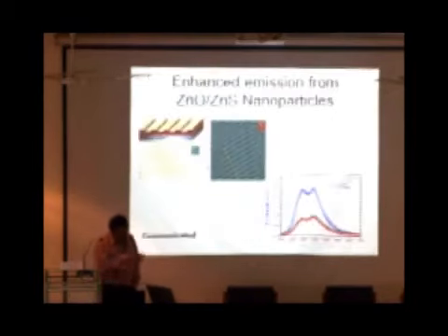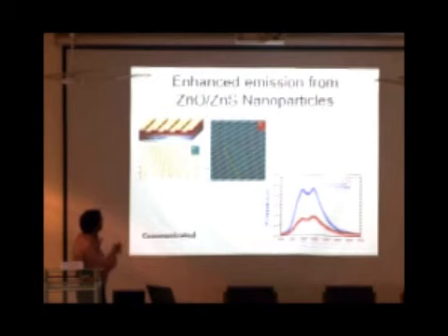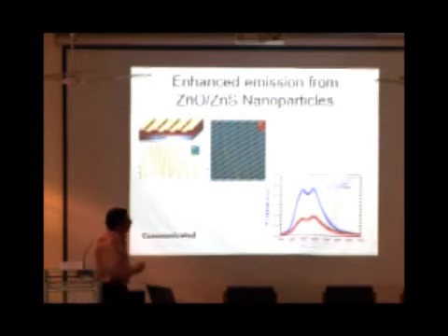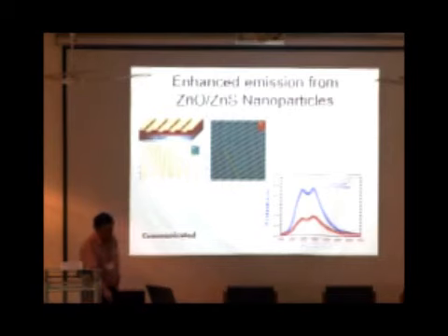What we have seen is that if you have a quartz dielectric and on top of which you deposit metal and put semiconductor nano dots - for example, this is zinc sulfide coated zinc oxide nanoparticles - you see an enhancement in luminescence by almost 2.5 times. We believe this is a plasmon mediated enhancement in the luminescence.